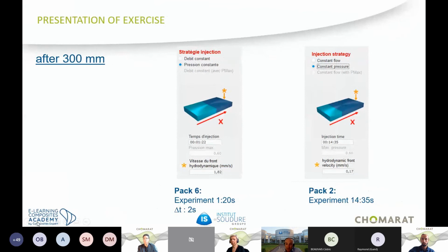On the other slide, we will do the same analysis at 300 millimeters, so we'll get a little bit more far away in the impregnation, and we still have the big difference either on simulation or on the experiment that is showing the deep impact in terms of impregnation speed provided by the use of G-flow. So something like one minute something with a G-flow and 14 minutes without G-flow. So this is a big difference, and we demonstrate this again thanks to the exercise, the trials, and the simulation.